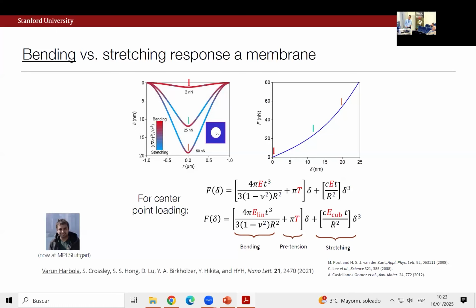So I'll justify it in 1 or 2 slides later, but let me just relabel things and say that for whatever reason, I'm going to worry about the possibility that the Young's modulus in the linear regime is different from that in the cubic regime. Okay? And again, pretension and bending terms in linear response, and symmetry allowed, the leading order nonlinear response is going cubically in this displacement. Okay, so here are the references. Again, a lot of this built on things that people developed initially in, for example, graphene experiments.